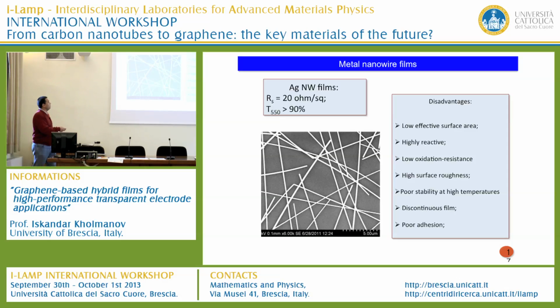Another disadvantage of these nanowire films is a very high surface roughness and a discontinuous film. Also, their poor adhesion and very low oxidation resistance, which I will show in the next slides.